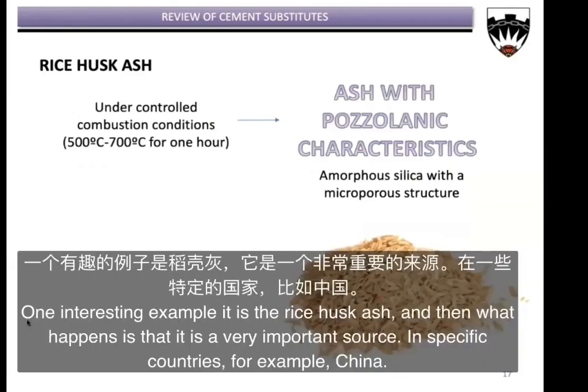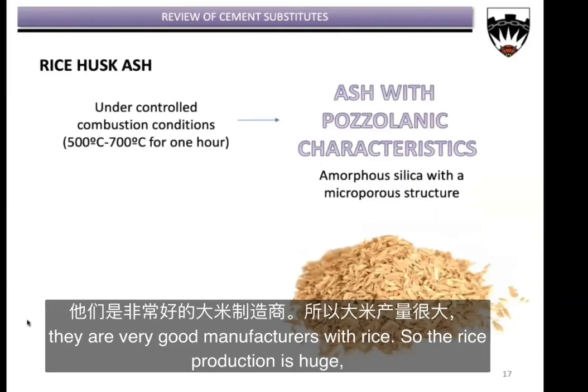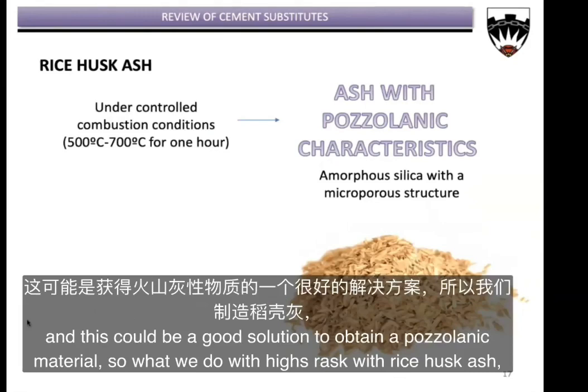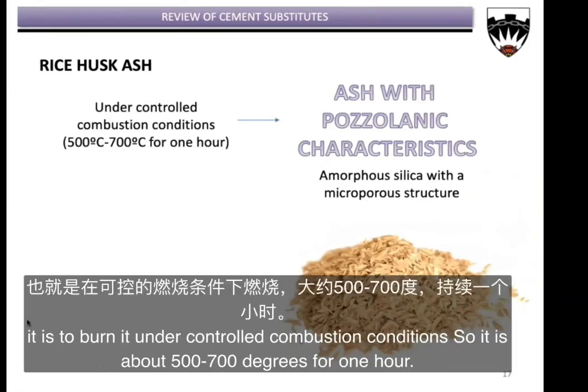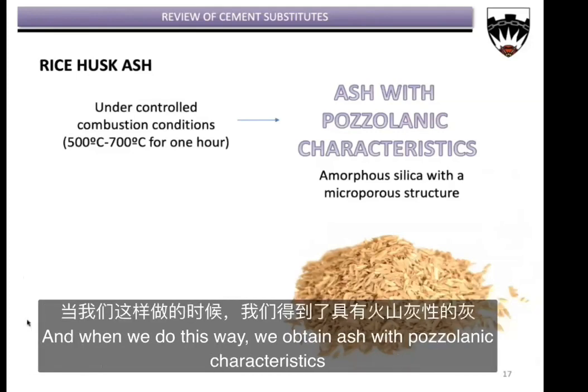One interesting example is the rice husk ash, right? And what happens is that it is a very important source in specific countries. For example, China, they are very good manufacturers with rice. So the rice production is huge. And this could be a good solution to obtain a pozzolanic material, right? So what we do with rice husk ash is to burn it under controlled combustion conditions. So it is about 500, 700 degrees for 1 hour. And when we do it this way, we obtain ash with pozzolanic characteristics.